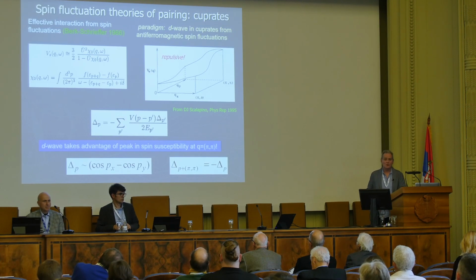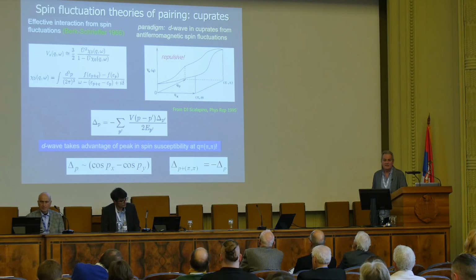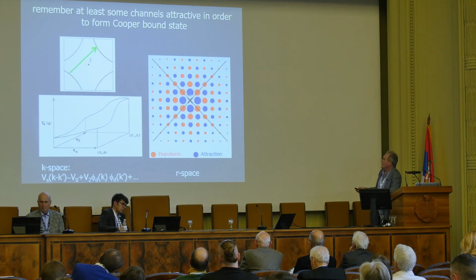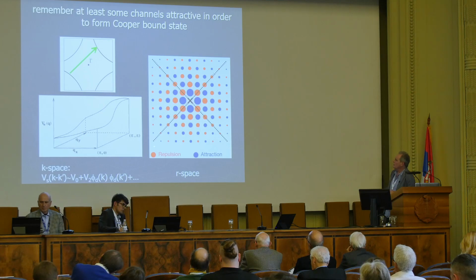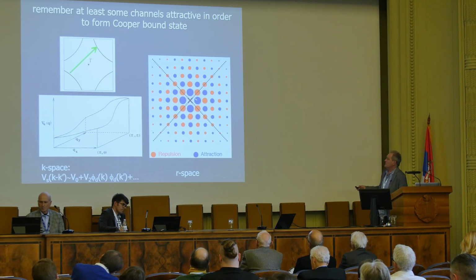It turns out, for those of you who know cuprates, this is precisely the form of the small energy Q-dependent magnetic susceptibility measured by neutron scattering in cuprate experiments. As students still have a hard time understanding where the attraction comes from, so sometimes it's useful to plot this in real space. So you put the first electron at the center, and then you plot the attractive blue or repulsive red for this particular interaction on every site of the square lattice. And you see that there are some sites which are blue, so that's where the second electron wants to sit, with the highest amplitude on the nearest neighbor.